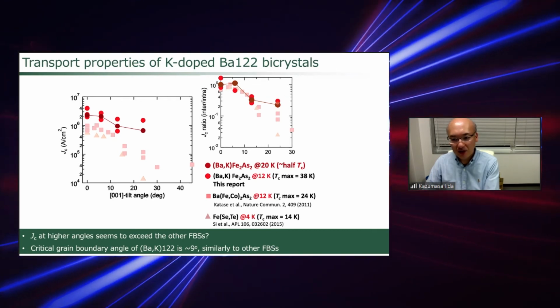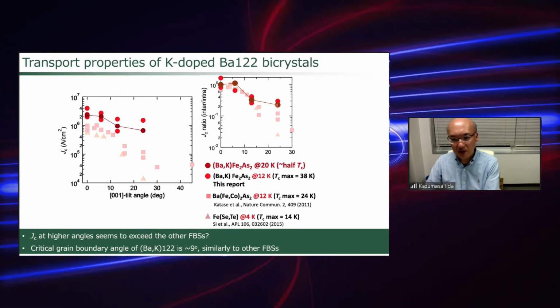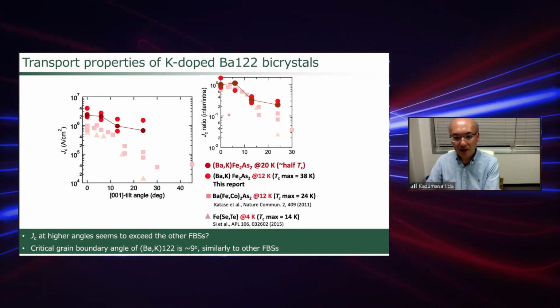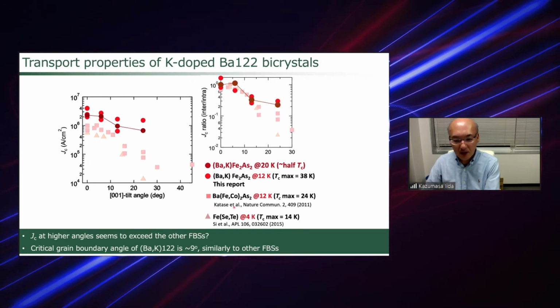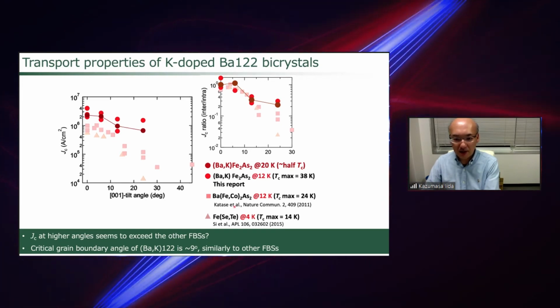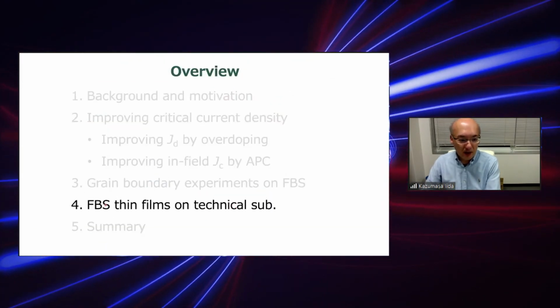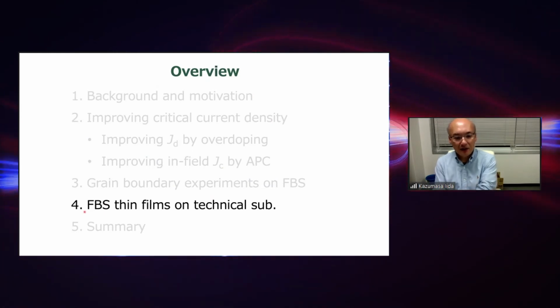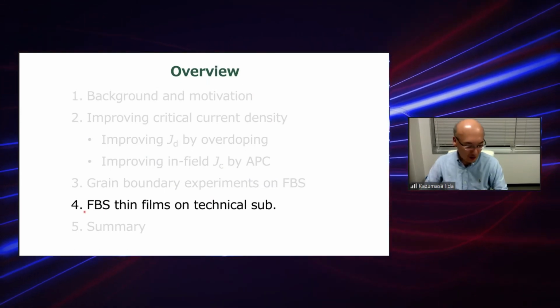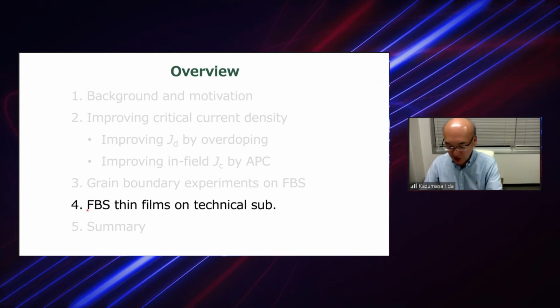But here, still, the grain boundary angle of 24 degrees is higher than in the other iron-based superconductors. Okay, now I'll switch to the thin films grown on the technical substrate. I have almost consumed the time.